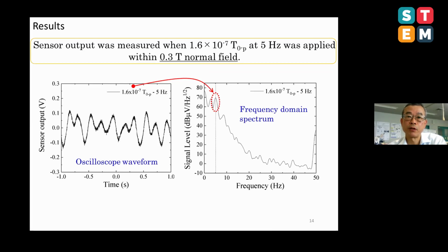This sheet shows the measured results when 1.6 × 10^-7 Tesla at 5 Hz was applied within the 0.3 Tesla strong normal field. The left figure shows an oscilloscope waveform, and the right figure shows a frequency domain spectrum of the same signal. In both figures, the sensing 5 Hz signal is distinctively observed.